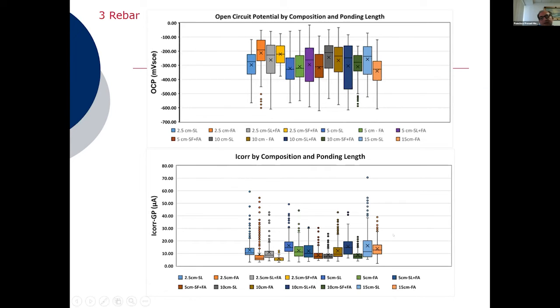And the bottom plots have a similar type of information, where you see the average corrosion current for the 3 rebar specimens group per reservoir size. In some cases, there were some values, likely at the beginning of the monitoring, where the corrosion current was larger, although in some specimens, more recent values appear to suggest that they have become more active as well.